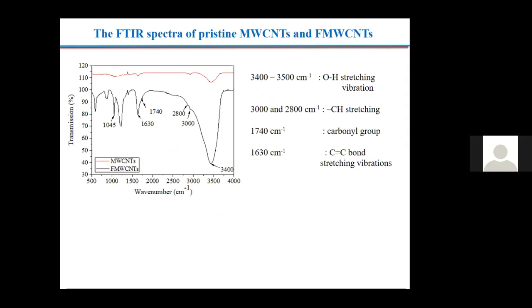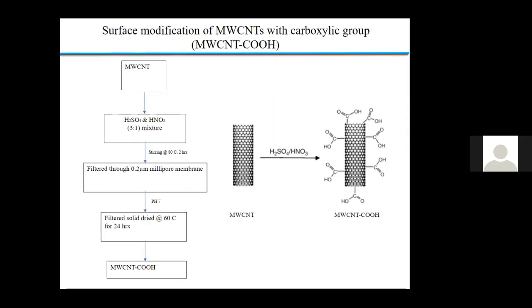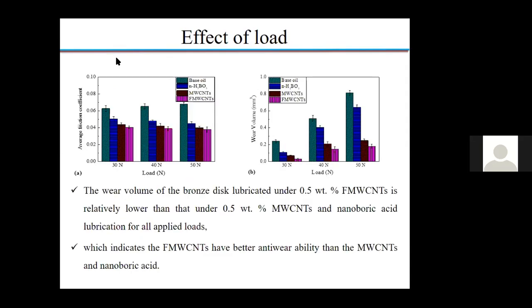and let us discuss the results obtained by using this. So in this case we have used multi-wall carbon nanotubes and functionalized multi-wall carbon nanotubes. Okay, so this is the base oil. H3BO3 was also used. Then multi-wall carbon nanotubes and functionalized multi-wall carbon nanotube particles were also used. Okay, so for the base oil, you can see the friction coefficient. Among H3BO3, multi-wall carbon nanotubes and functionalized multi-wall carbon nanotubes, functionalized multi-wall carbon nanotube provided a better reduction in average friction coefficient. Okay, so this is the advantage of functionalization.